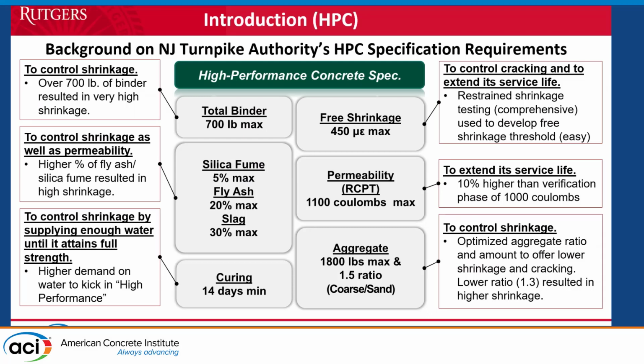So this is the basis for what we did almost 20 years ago. We introduced high-performance concrete to the state, and New Jersey DOT and the New Jersey Turnpike, between the two of them, they have about 6,500 bridges, and the average age of these bridges is about 50 years, so they exceeded their design life. So they ended up changing or replacing a lot of their bridge decks. So they have a lot of what they call reconstruction by removing the bridge decks and placing high-performance concrete at the time.